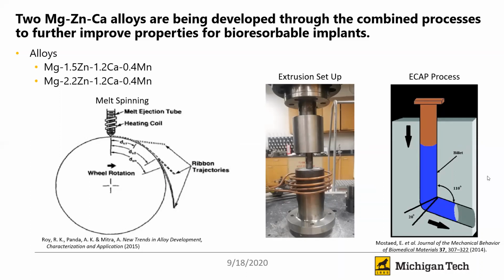And then after extrusion will be subjected to ECAP processing, as seen here in this picture on the right, to develop an alloy with a reduced number of precipitates and smaller grain size, which will aid in corrosion behavior and mechanical strength and ductility increases.